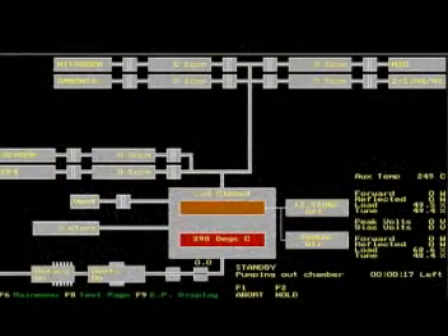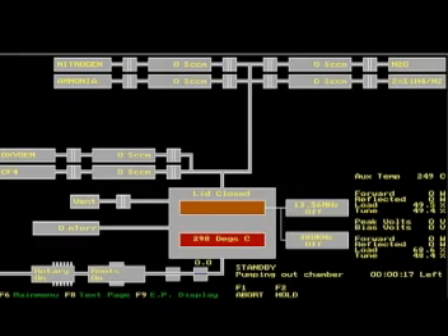The first phase of the process is gas stabilization. The process gases are dispersed at the set point rates. The process pressure is attained through throttled pumping. The pressure and flow rates are maintained for 30 seconds such that the chamber can reach equilibrium. The next phase is deposition. Here, the power is applied to the electrodes and plasma is created.